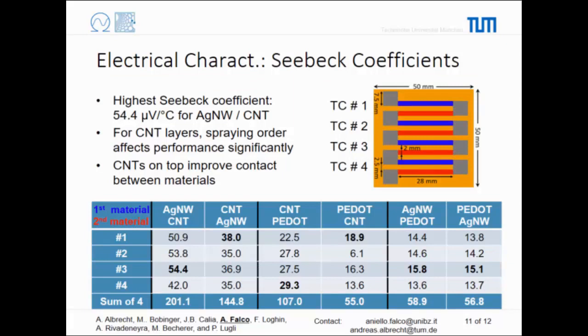And that is due to post-processing that you need to apply to the materials for them to function. So for instance, carbon nanotubes are immersed into a polymer matrix that needs to be removed after the dispersion. And so this could somehow affect also the underlying layer of silver nanowires. The same for silver nanowires. They have an insulating agent called PVP that has to be removed before it can really work. PEDOT PSS needs a thermal annealing, and this could affect somehow the results also of the underlying material.